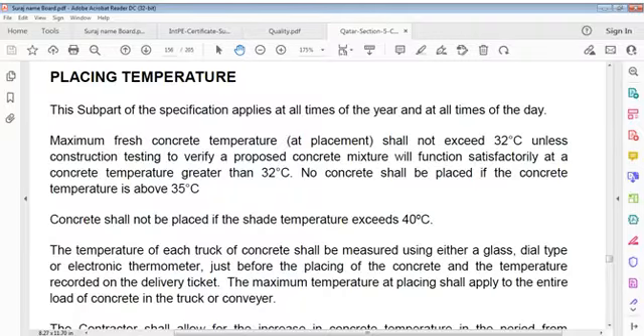Placing temperature, I'm back with that, okay? So we can say placing temperature. This is a part of specification, as I discussed before. It says that concrete temperature should not exceed 32 degrees Celsius. That's very important. And if you can prove that concrete is not harmed, it can rise up to 35 degrees.